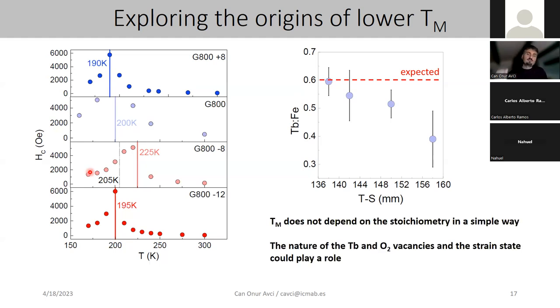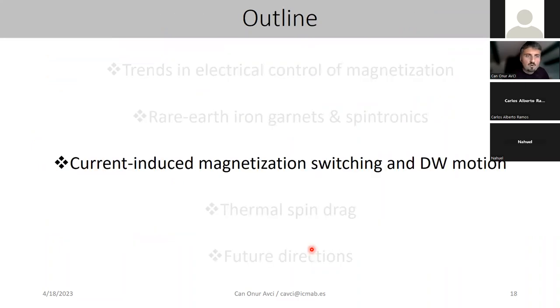Therefore, the stoichiometry, as opposed to what is commonly believed, does not really play a role in the magnetic compensation in these films. And we believe that the nature of the terbium and oxygen vacancies and the strain states could play a more significant role. So we are right now doing some additional experiments to figure out what's going on in these films.